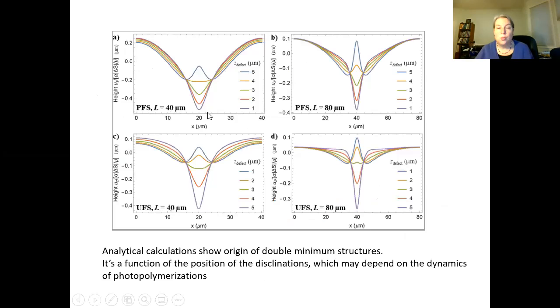And then the other question is, what about the double well structure? Here my husband, Jonathan, came to the rescue. We had done some simulations, but he said, if the displacements are very small in this film, we could make some very simple assumptions about linear elasticity. He did analytical calculations, and what he discovered, which our simulations also showed, is that if the disclination forms too close to one of the two surfaces, you get a double well. If it's in the middle, you get a single well. Pretty simple. You're trying to engineer something, it's good to know what's going on.